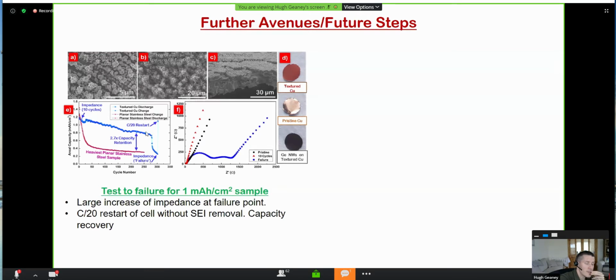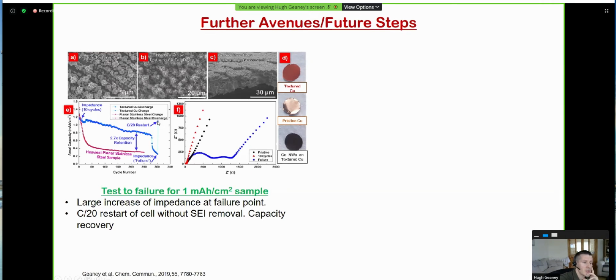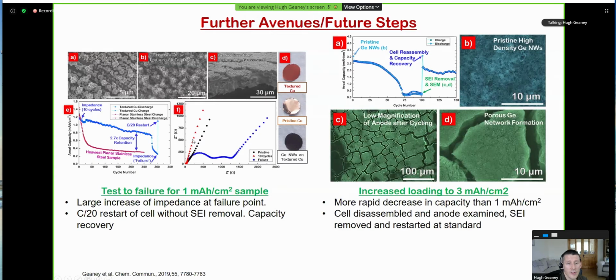So what we found is if we actually disassembled the cell here and then reassembled it with a fresh lithium counter electrode, that the performance jumped back up here again once we did it at a C/20 restart. So this was done without an SEI removal as well. So this is just down to the way that the impedance occurred on the electrode. So essentially what had happened was that the processes that we were looking to do in terms of the lithiation had moved out of our potential window that we were investigating. In terms of increasing the loading even further, we could bring it up nearly to commercial levels in terms of the areal capacity. So we could bring it to nearly 3 milliamp hour per centimeter squared.